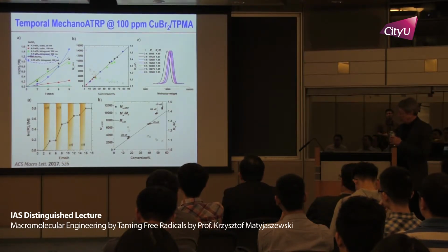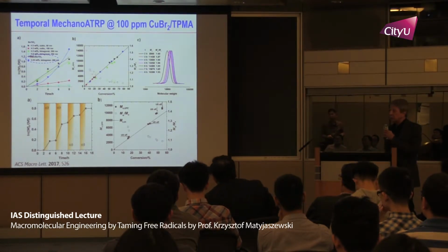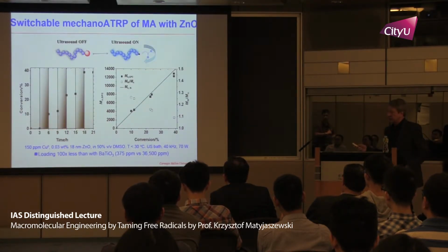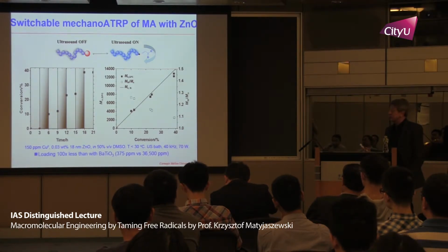But if you look really what happens in this system, you are using a very large amount of catalyst. In fact, it's around 5 to 8%. So the question is, can we go to lower amounts? We switch first to zinc oxide. Zinc oxide, in that case, is in the amount not 5 to 8%, but 0.038%, so 100 times less. And a similar effect, on-off, on-off, on-off. Good control of molar masses, low dispersities.